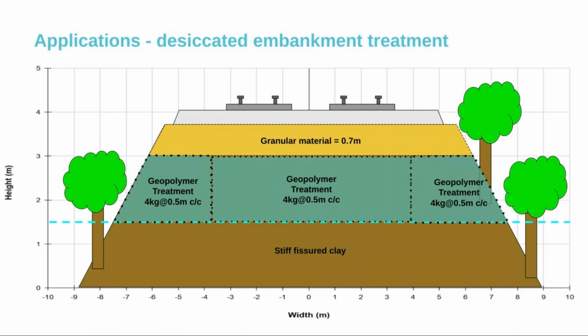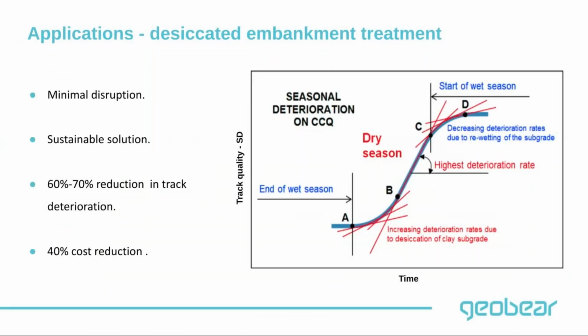And what you would do with that, basically, you would end up with a situation where you kind of freeze the deterioration cycle, you intervene with the deterioration cycle. So instead of having a deterioration where you start with low deterioration, high in this dry season, then low again, you would almost freeze the deterioration cycle to something similar to what you would normally get from the wet season. We've done a lot of analytical modeling with this, and we've got to the conclusion that we can actually reduce the embankment deterioration by almost 60%.